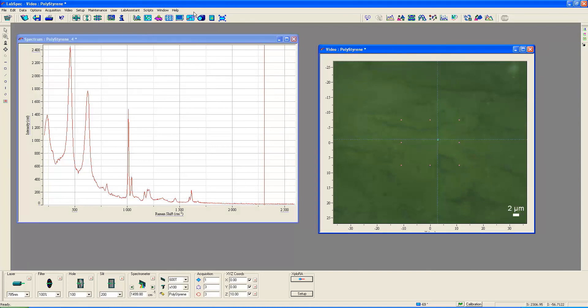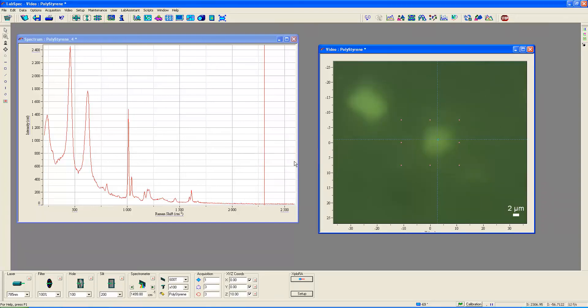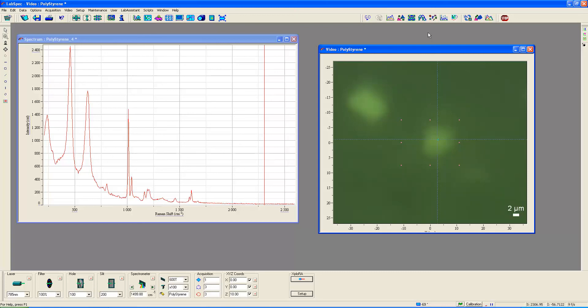Now, let's go back to our video. And we click the video. And the instructions tell us to move the turret to position 2, which I do. And lo and behold, what do you see is below the surface these white particles. Well, these are basically little clumps of titanium dioxide that have aggregated. I presume they would have been put in to disperse uniformly through the polystyrene. But there are areas in which they have aggregated. And so if we get below the surface, then we can find this confocal. We can confocally find these areas of different composition.